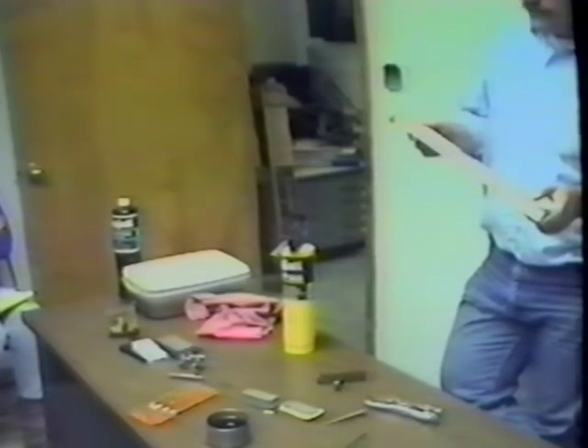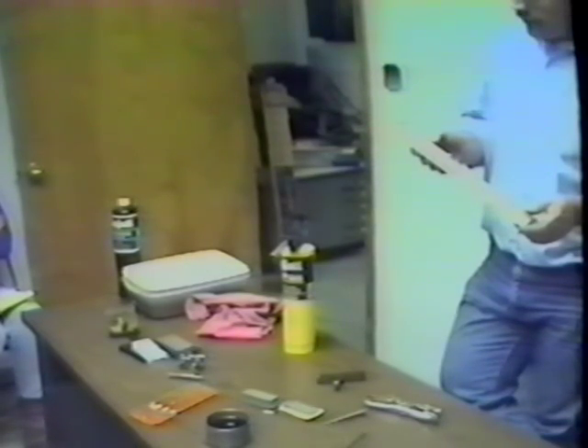Does that steel come with the instructions on heat treating? Usually they give it to you. Right here, hardening, it says preheat thoroughly at 1200 degrees Fahrenheit to 1250, so we were right between there. We went right on through that. Then heat to 1450 to 1500, depending upon section size. Hold until uniformly heated through. Quench in warm, thin quenching oil at about 125 and temper immediately. There it says temper immediately.